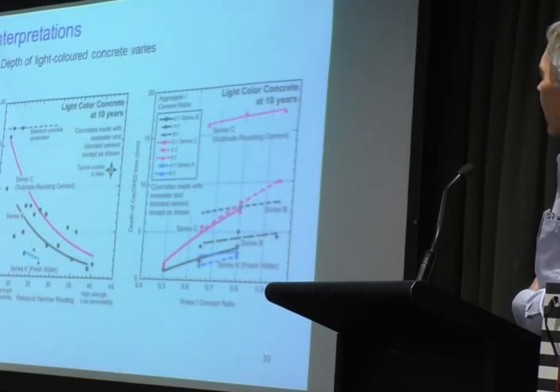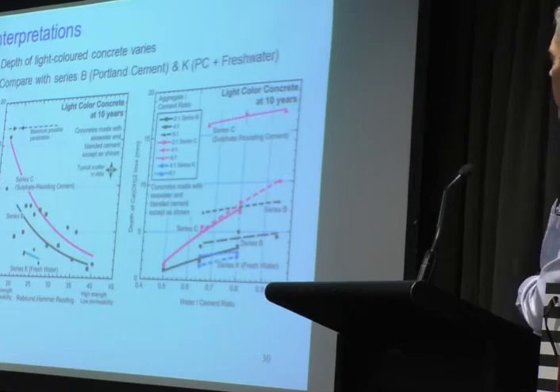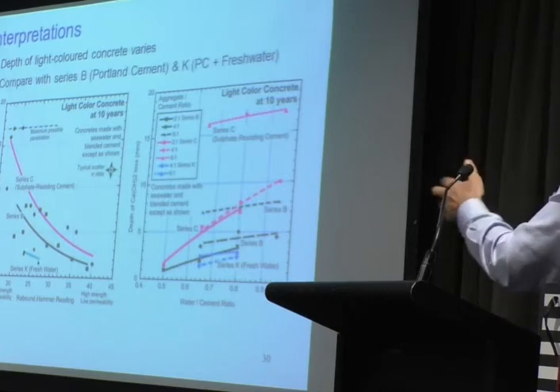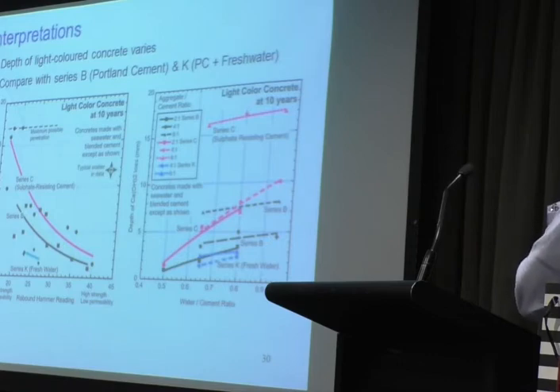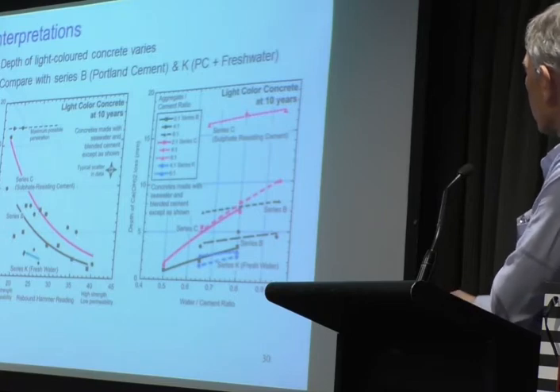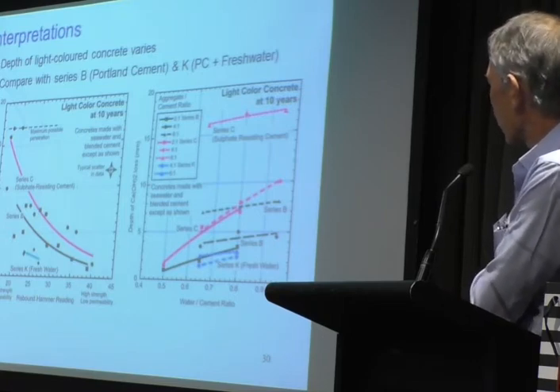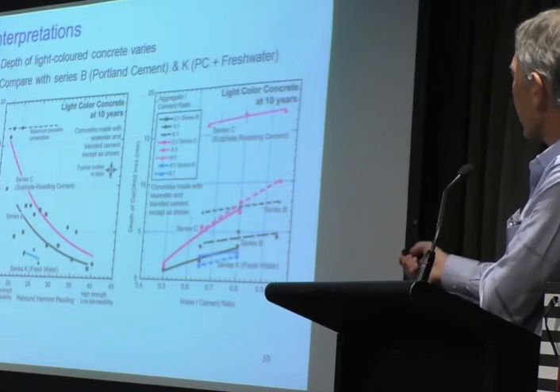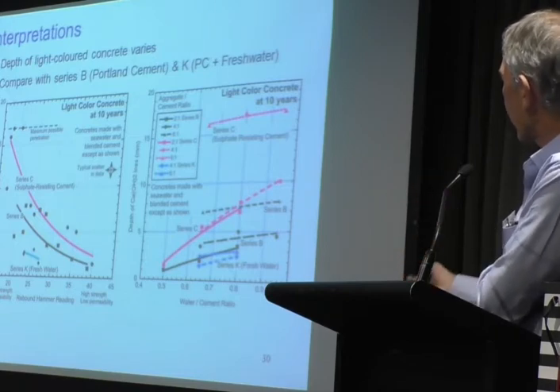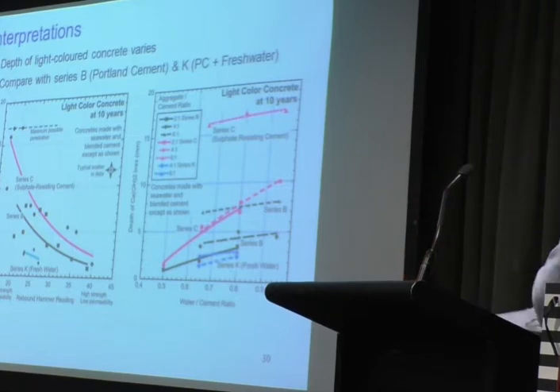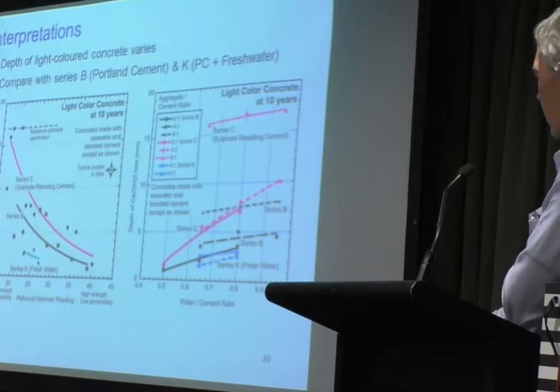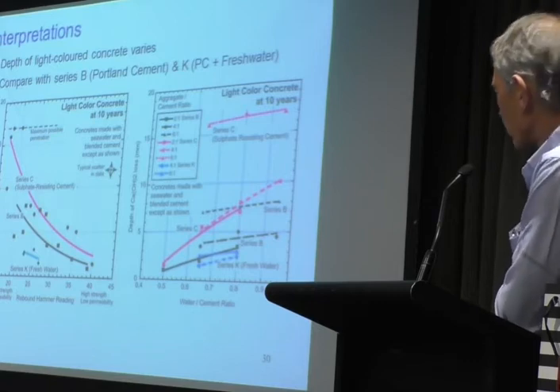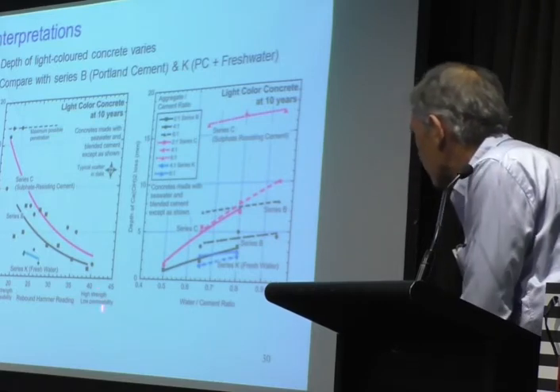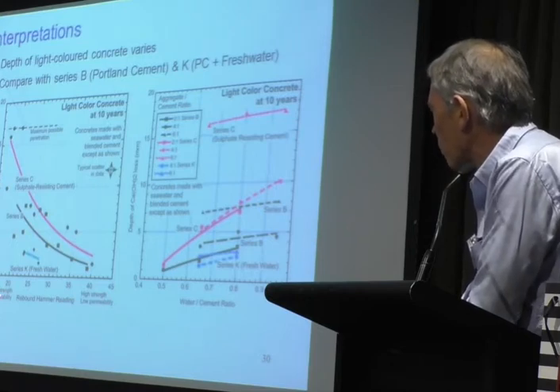If we then look at the depth of the light-coloured concretes between the Series B, which is the ones I've been describing to you, for Portland cement, and also sulfate-resisting cement, which is the red ones. The B ones are the Portland cement, and K is some samples we made with fresh water. And let's just talk about this side only. This is Schmidt hammer readings, which is a surrogate for permeability, if you like. So these are high strength, low permeability, and high permeability there.